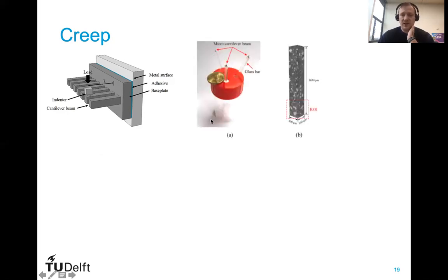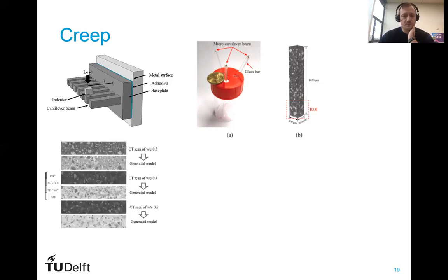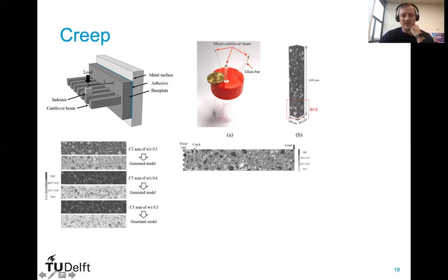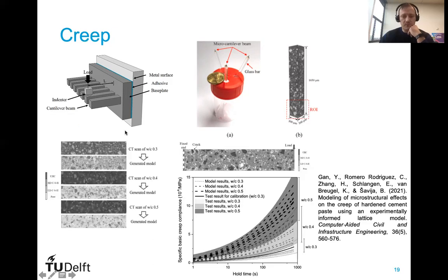What we also did was that we created small specimens that were scanned using an X-ray CT. And then from there, we can easily segment different phases within the cementitious matrix and use that as input for our simulation. So for different water cement ratios with segmentation procedures, we could generate inputs for our numerical model of creep. So we have experiments of creep, we developed a numerical model of creep, and we simply repeat the same thing. So we have here a cantilever loaded at the tip, same thing as we do in experiments.